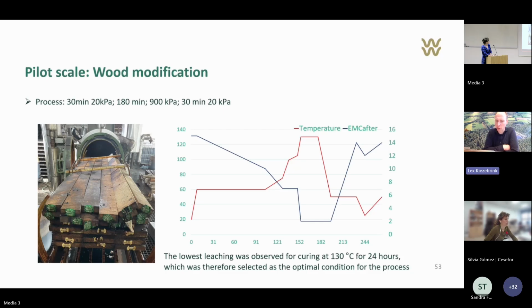In this stage we could also control the humidity, because you have bigger sizes of board. We have to dry the moisture carefully out of the wood, otherwise you will get cracking. So you can see that in the first stage, after heating, we are at constant temperature, and we slightly reduce the humidity to make sure that...